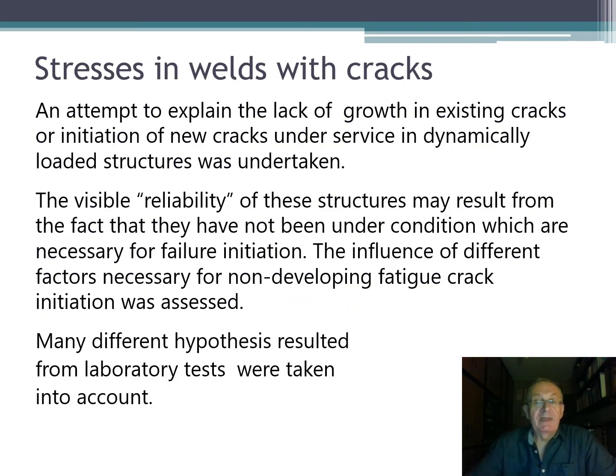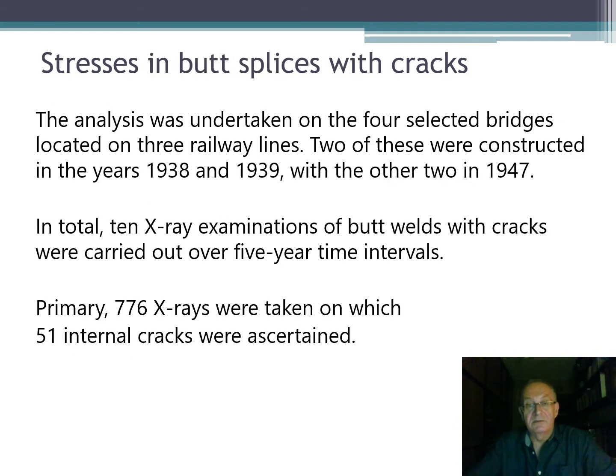An attempt was undertaken to explain the lack of growth in existing cracks or initiation of new cracks under service in dynamically loaded structures. The durability and reliability of these structures may result from the fact that they have not been under the conditions which are necessary for failure initiation. The influence of different factors necessary for non-developing fatigue crack initiation was assessed. Many different hypotheses resulting from laboratory tests were taken into account.